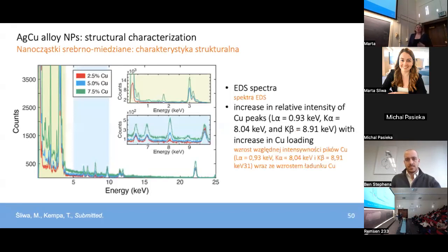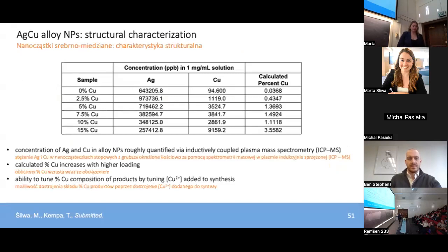So we then also went on to both qualitatively and semi-quantitatively determine the amount of copper in these particles as we increase that nominal loading. Here we see an overlay of EDS spectral data, which indicates an increase in the relative intensity of the peaks corresponding to copper as we go from 2.5 to 5 to 7.5 nominal copper loading in these systems. We also further confirmed the concentration of copper using ICP-MS and saw that there is an increased calculated percent of Cu as we increase that copper loading.